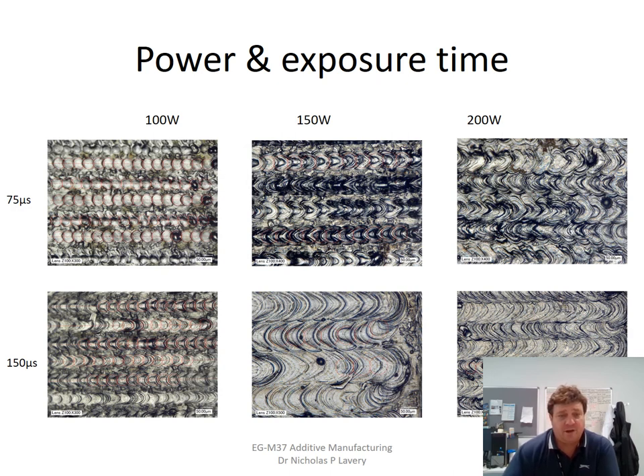So here's another example of what the tracks might look like. We've varied the power and the exposure time, so we give a higher power, 100 watt, 150 watt, or 200 watt, and then we increase the exposure time. And you can see that you can almost have very distinct laser spot welds without much overlap between the adjacent tracks. As the power goes up, we start to get a mixing of the tracks so that we're actually joining up. So this is going this way, and then that's coming back this way. And you can see that we've actually got an overlap now, even though the hatch spacing is relatively wide. And again, that becomes even more exaggerated as we keep the laser on for longer.